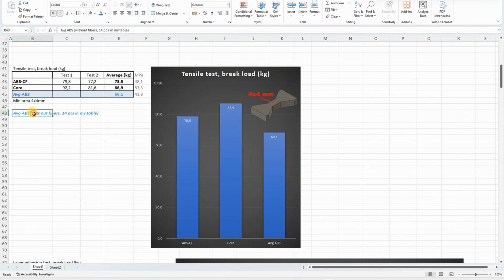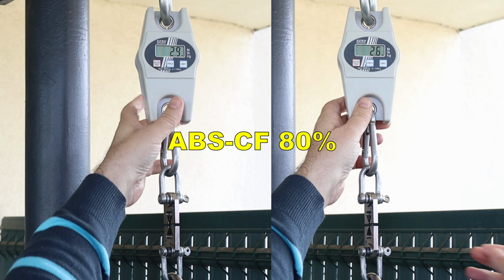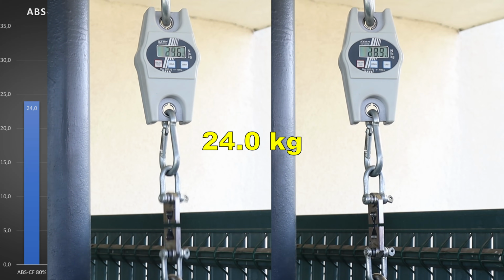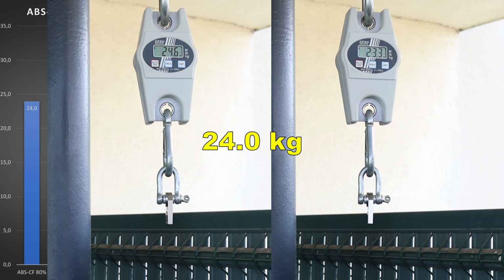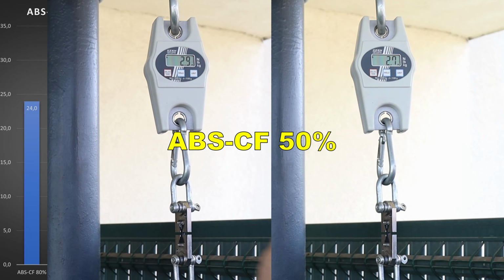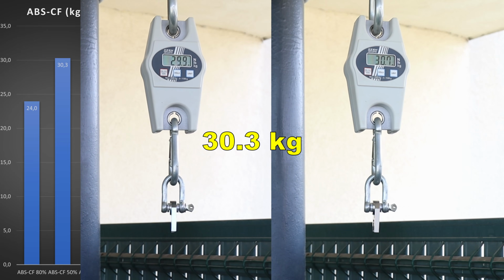I will include the data for the average ABS, which is calculated from 14 pieces from the pattern summary table. And we can see that the core version is stronger than the regular ABS-CF, but both are stronger compared to the average ABS. Layer adhesion tests with vertically printed objects. And this is the value for the 80% part cooling and now the 50% max part cooling.